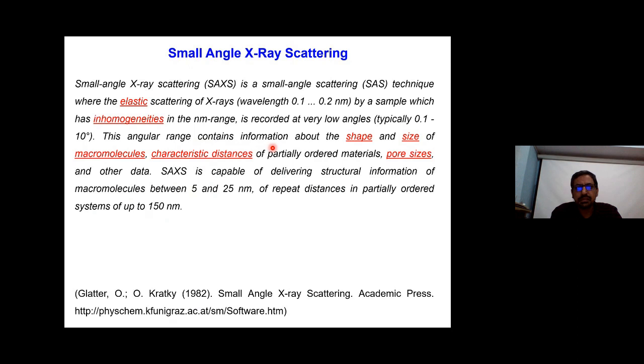Okay, the typical information which can be achieved is shape of the material, size of the system of macromolecule, characteristic distances, pore sizes, etc. And SAXS is capable of delivering structural information of the order of 5 to 25 nanometers for systems which are partially ordered up to 150 nanometers. Now, this was actually mentioned some time back, these numbers. Now, with the advent of new technologies, these numbers keep on shifting to higher values. So now you can obtain information up to 300 nanometers as well, given the new geometries we have.